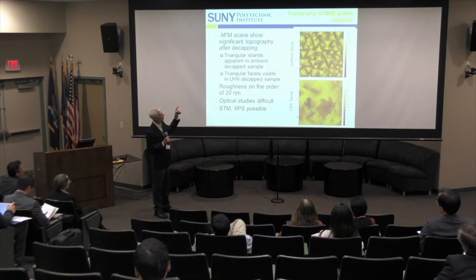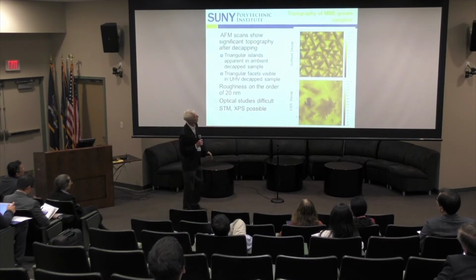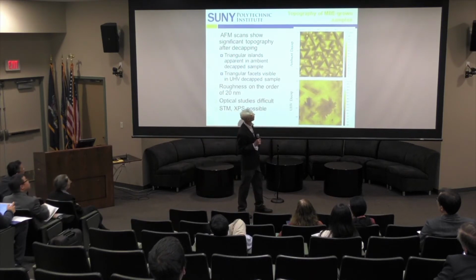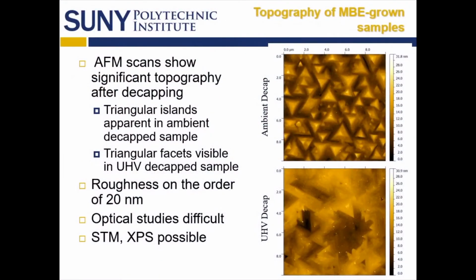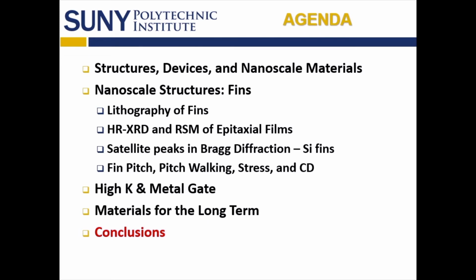We got some MBE grown bismuth selenide on sapphire, and the STM and AFM data all look the same. They have these really unusual trigonal pyramid structures, and you can see in that structure that the triangles, some are pointed up, some are pointed down, so that the crystal structure is rotated 180 degrees. It's easy enough to see that in an X-ray diffraction pattern, but the roughness of these materials, if you're trying to use them in a device, again, is something where a probe microscopy method gives you useful information.